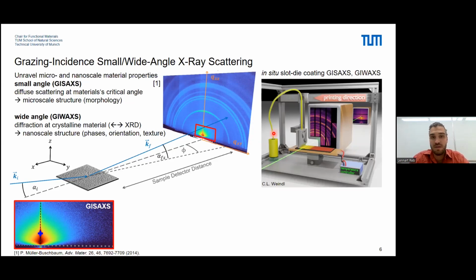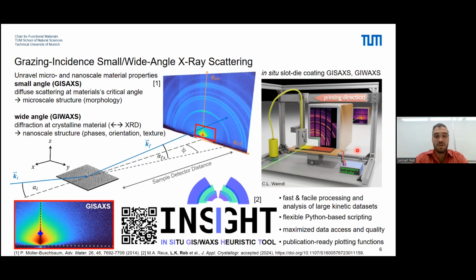So here, for example, there is a rendering of an in situ slot die coating process at the beamline, where we could measure GISAXS with the rear detector and GIWAXS with the close-by detector for the large angles, and basically follow the kinetic processes during printing and crystallization of perovskite. Then I want to quickly introduce you to a new software that we could develop during the time of COVID, because the labs were closed, so we could work a lot at the computers. It's called INSIGHT. It stands for In Situ GISAXS GIWAXS Heuristic Tool. And it's a Python-based scripting tool, which allows for fast and facile processing of especially large kinetic data sets.